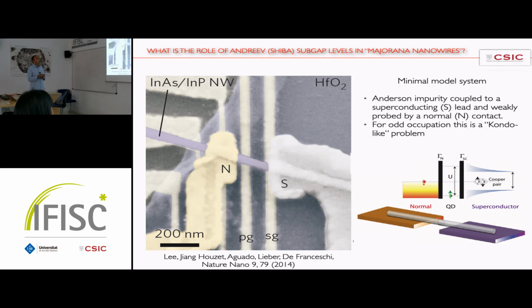And the point is that for odd occupation, when this quantum dot has odd occupation, this is a spinful quantum impurity. It's like a Kondo problem. But now this Kondo problem is modified by the fact that you are coupled to a superconductor instead of a standard metal. So it's like the superconducting counterpart of a Kondo problem. Okay? And maybe you also want to consider the coupling to this normal lead that you use in this transport configuration. All right, so you have a spin coupled to a superconductor.